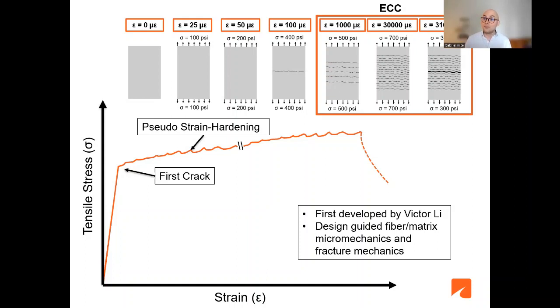Contrary to common belief, usually when you design a conventional fiber reinforced concrete, you try to maximize the bond, get the highest bond possible of the fiber with a cementitious matrix. But in ECCs, this is not the case. You need to have a balanced bond so that the fiber can pull out of the cementitious matrix. And this allows for this multiple cracking behavior of the ECC and the ductility. Also, what these principles tell us is that we need to design a composite where the cementitious matrix is very brittle. And again, this also goes against what we typically want to achieve in concrete materials. We actually want a concrete material that does not crack. Well, here in the ECC, you want a cementitious matrix that is prone to cracking to enhance this pseudo-strain hardening behavior. So this is a very interesting design theory behind these ECCs.